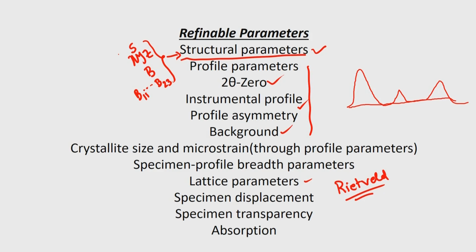So, when you do the so called Rietveld refinement, you need a starting model. The starting model can be generated the way we discussed, or it can be obtained from the database. See, if you go to the ICSD database and look at different kinds of bismuth vanadates, there is a good possibility that there may be a structure very closely related to this structure with the cell dimensions agreeing nearly the same. In such a situation, we can take those coordinates, put them in as the structural parameters and go ahead and refine. Then it will be a successful refinement.